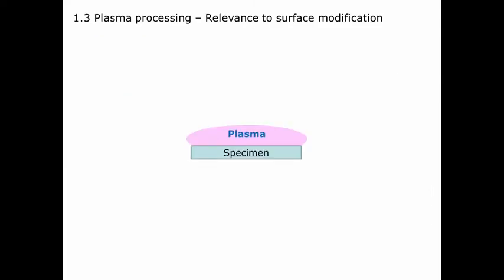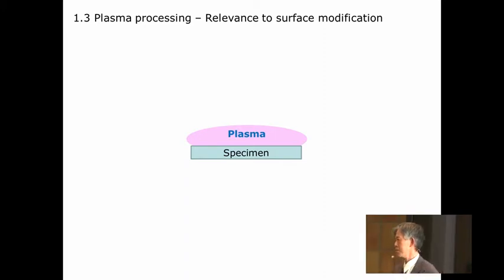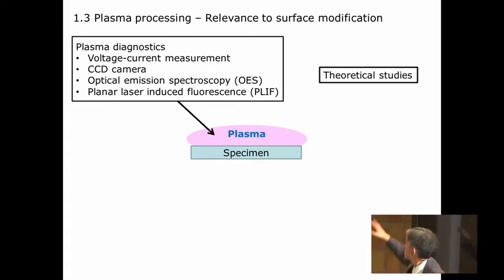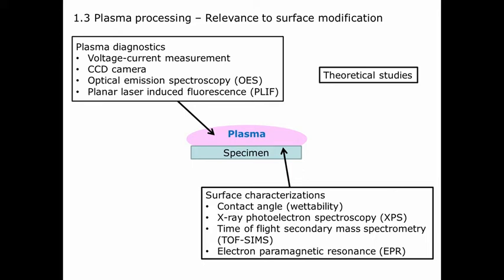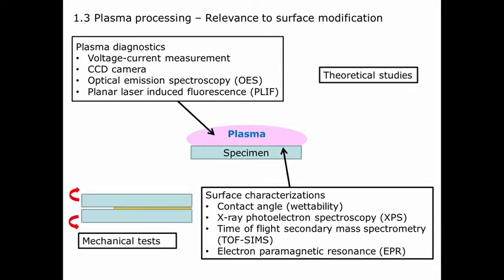Okay, then it is clear that I'm not only working on plasmas, because I need a material to be treated. Then I need some testing for the treated ones. But first of all, in my research, I have to diagnose and characterize the plasma by various techniques and have some theoretical approach. But characterization of the treated, modified surface is also important. Having the wetting test and also elemental compositional analysis and detection of radicals in the materials, which I have used in this presentation. But for adhesion research, it is also a must. We have to verify that the treatment effect is useful for eventual improvement of mechanical properties.